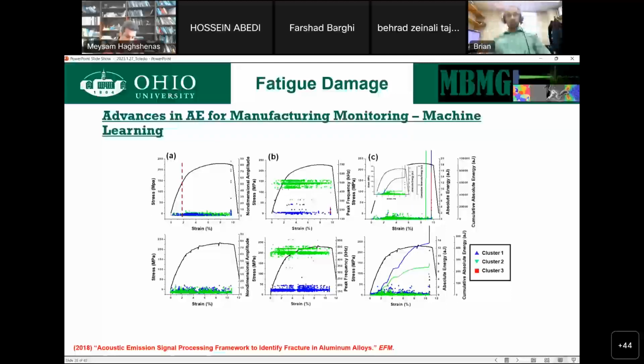And so what we can do is take what we learned looking at a few waves and extrapolate that. What I'm showing you here is that same basic test from before. We have a monotonic load on an aluminum sample. We have data that we collected in acoustic emission, and we performed a clustering method. In this case, it was simple k-means clustering, using about 7 of the features that you can use to describe a wave. And we identified 3 clusters. One with a high amount of amplitude, one with a peak frequency content in that 500 kilohertz range, one with a content down around a little bit below 200. And then there's the red cluster that really is just extremely loud signals.